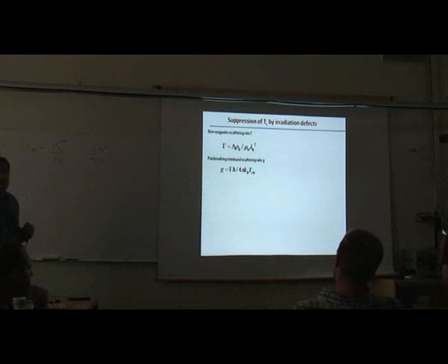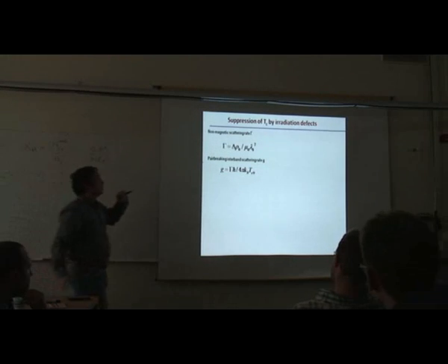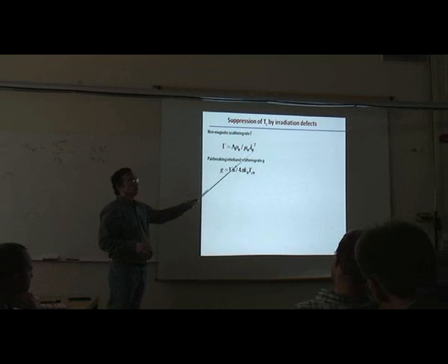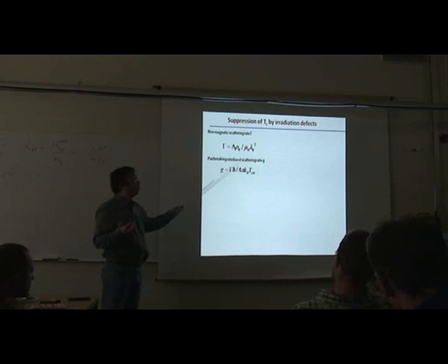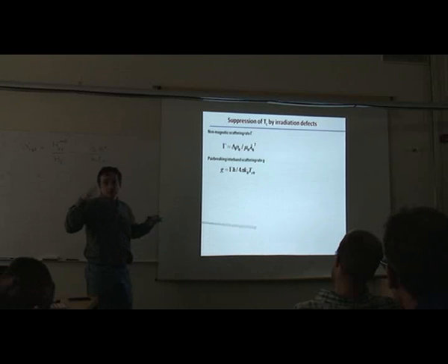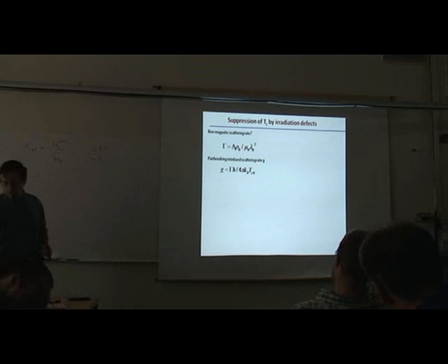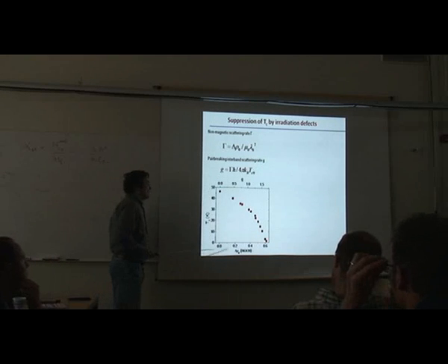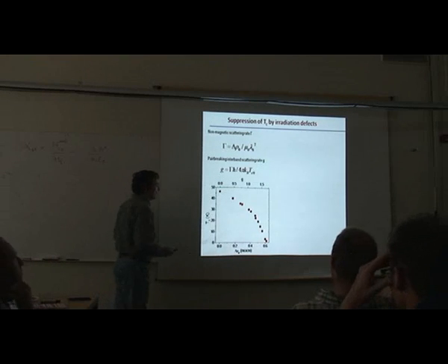So then we can calculate the scattering rates using the Drude formula. This is a fancy way of writing down the scattering rates, delta rho, and this is the magnetic penetration depth. The reason why we wrote it this way is that the carrier density cancels out here and here using the Drude formula, and we only have the scattering time. And that's what we need to calculate from the models. Okay, so if I plot Tc as a function of delta rho, it drops like this.